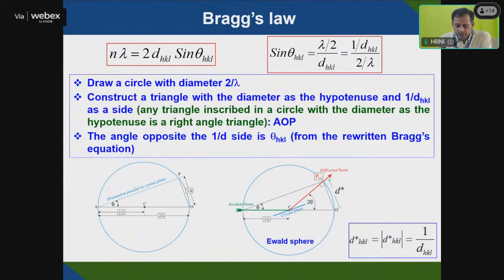You can rewrite the same equation. If you take the 2 to the opposite side, sine theta equals lambda by 2 d HKL. If I take n equal to 1, lambda equals 2d sine theta, then sine theta equals lambda by 2 d HKL. So I can write 1 by d HKL on the lower side, and you get the equation sine theta equals 1 by d HKL divided by 2 by lambda, which is the modified Bragg's law. So sine theta equals 1 by d HKL into 2 by lambda.